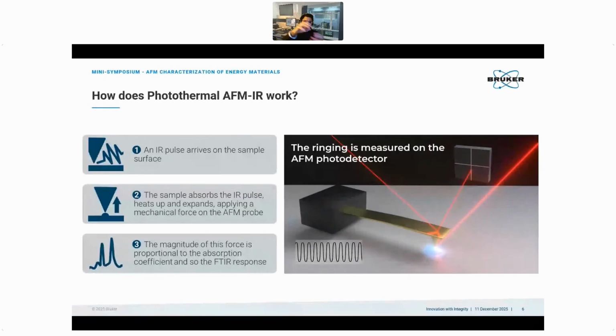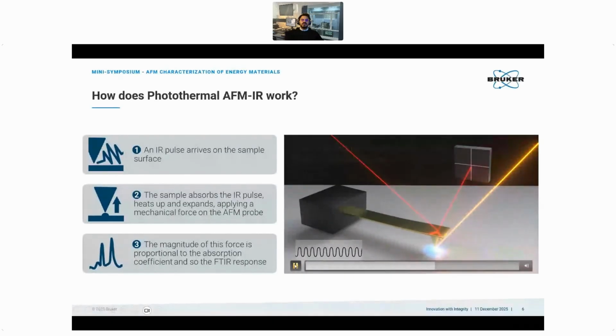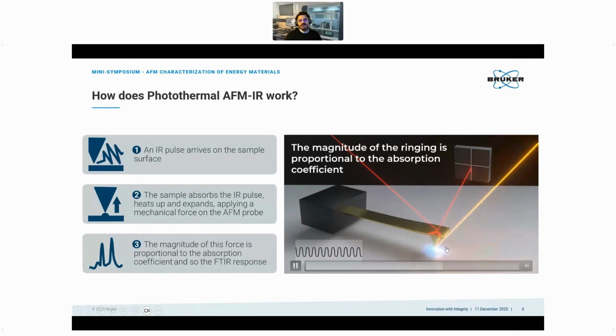Every time it's on, the sample will expand, and when it's off, it will retract, and this happens at the same frequency as the pulse. If you watch here, the sample going up and down is activating the cantilever because it is pushing it up. If the frequency of this pushing up and down, which is the frequency of the laser pulse, matches a contact resonance eigenmode of the cantilever, then the cantilever will get into very high amplitudes of vibration in contact, which enhances the sensitivity of our measurement.